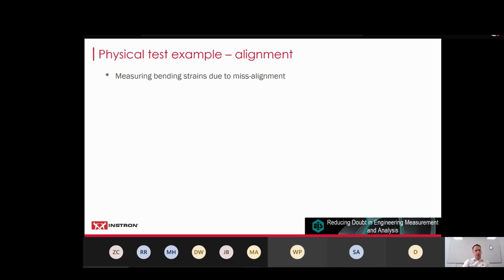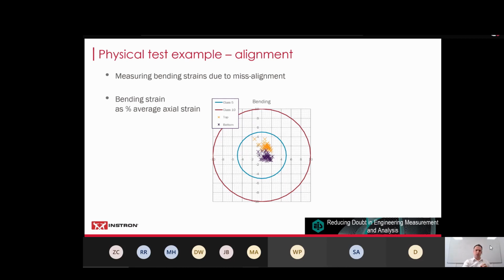Let's just briefly look at an example of this. There are techniques by which you can set up and measure this by instrumenting a specimen. People don't usually do this with each individual specimen. You do effectively a type verification, at least for the system, ideally each time you run each new batch of testing. So this is a polar plot of bending strain on the two axes, so left and right across the machine, out and front and back. Now, this is bending strain as percent of the average applied strain.